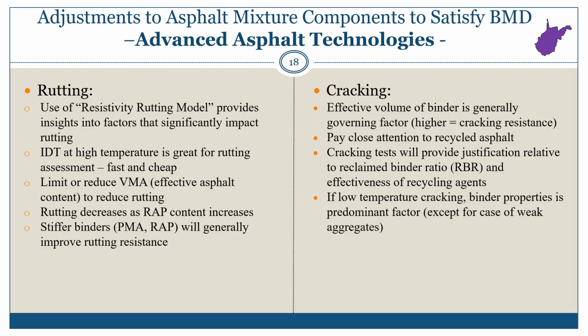On the cracking side, well, again, because it's balanced mix design, what you do at one end of that seesaw will affect the other. On the cracking side, if we want to improve cracking, we have to increase the effective binder, which is basically opposite of rutting. We have to make sure we pay close attention to the recycled asphalt, not just the content, but also the source. Make sure that we have a proper justification relative to a reclaimed binder ratio and the effectiveness of recycling agents.